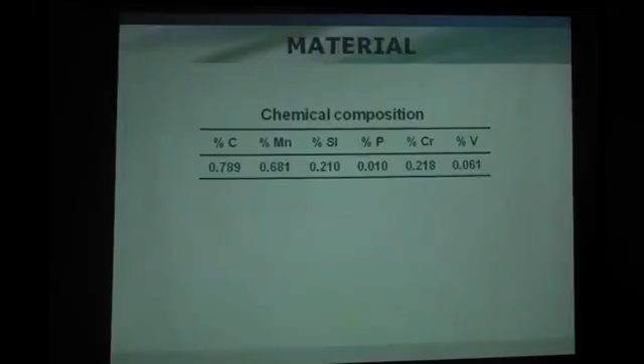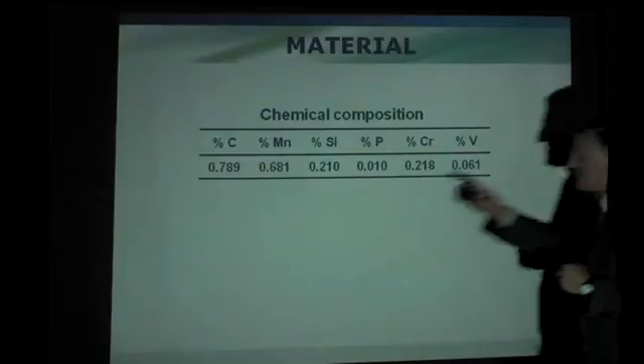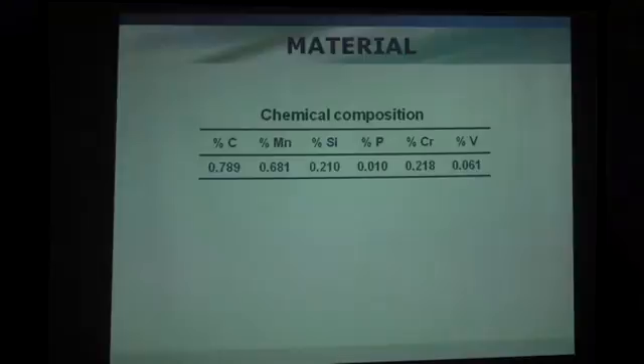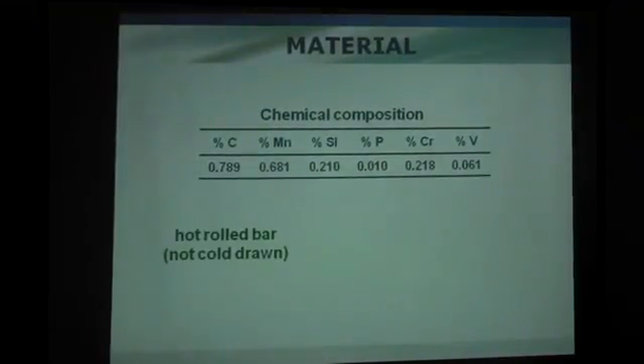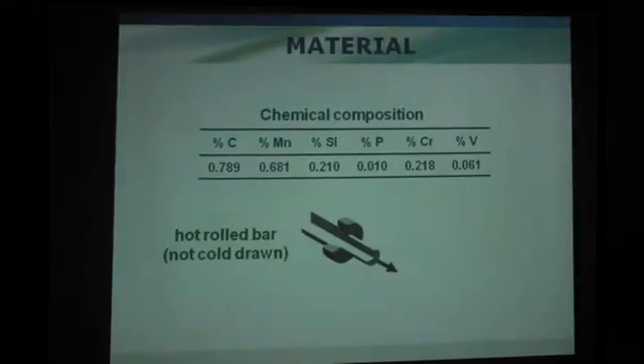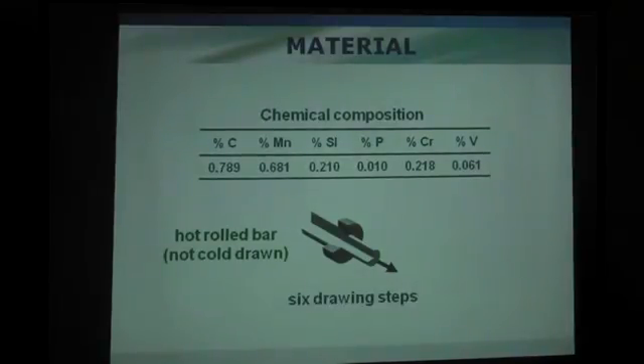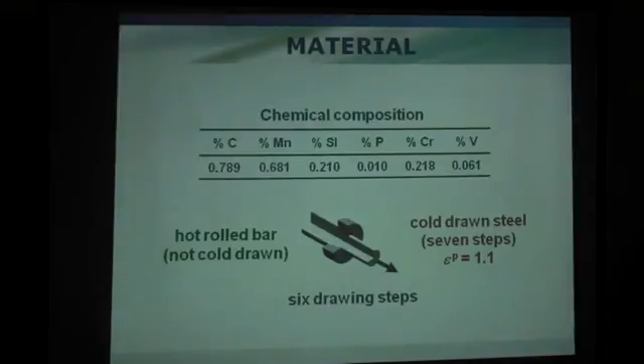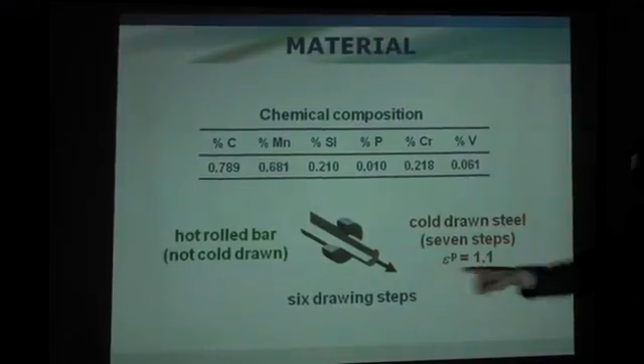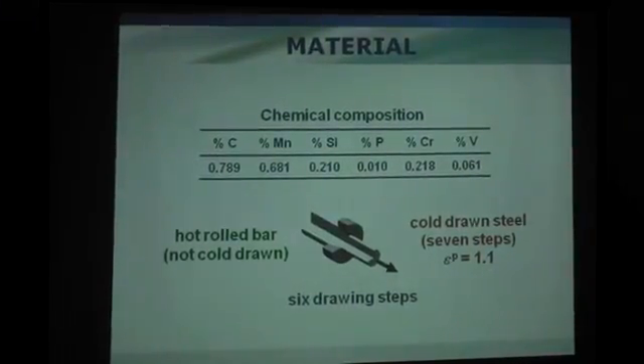The experimental procedure, chemical composition. This is a quasi-eutectoid steel with, roughly speaking, 0.80% of carbon and other chemical components, and the base material is a hot rolled bar, not cold drawn at all. And after several steps or stages of cold drawing, we obtain a heavily drawn material after 6 drawing steps. Cold drawn steel, commercial prestressing steels, after 7 steps of drawing with a cumulative plastic strain of 1.1.